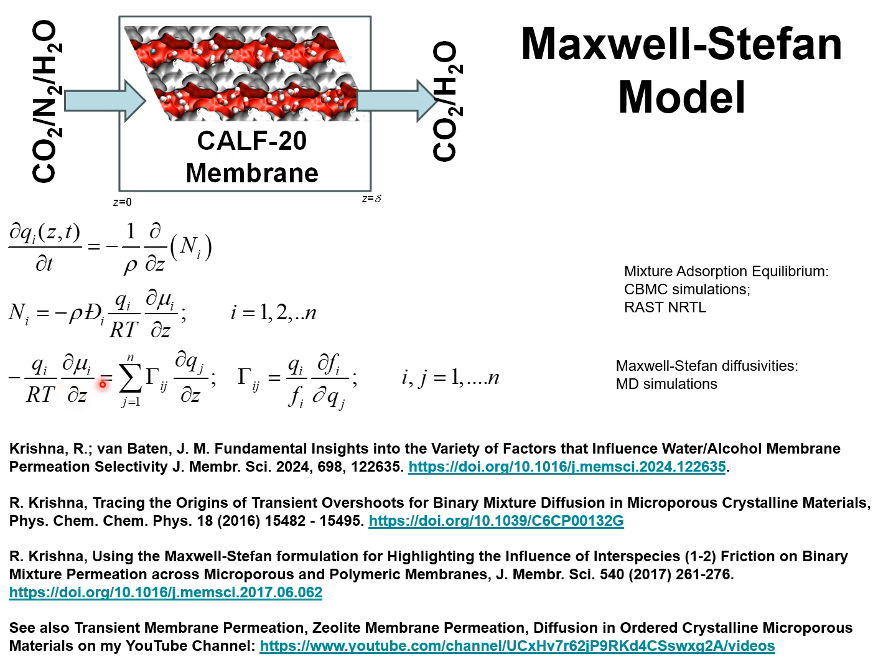The gradients in the chemical potential may be related to the gradients in the molar loading by introducing a matrix of thermodynamic correction factors that is given by this expression, where f sub i represents the partial fugacities in the upstream compartment of the membrane. The thermodynamic correction factors are determinable from the expressions for the description of mixture adsorption equilibrium.